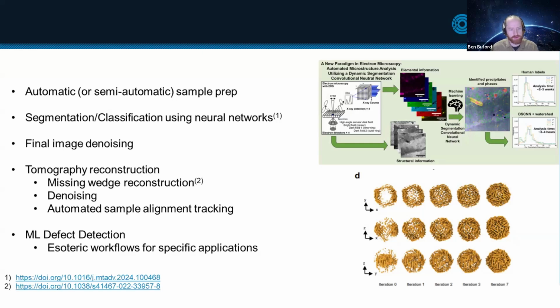And then also there are ways to use automated sample alignment tracking, where you embed a gold bead in your sample, and then either have the tool adjust to reposition that over time as you rotate to correct for any drift, or use that for alignment during the reconstruction process.